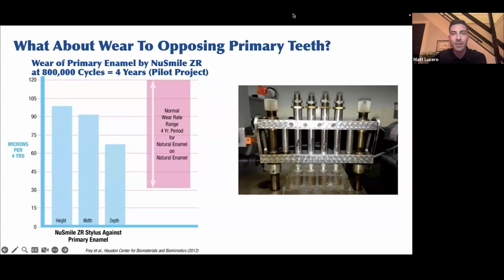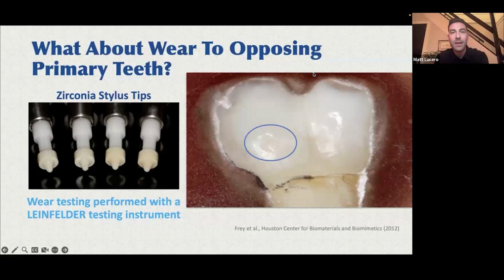So even with the zirconia restoration, a highly polished, glossy restoration, you're not going to get much wear to that opposing dentition. It falls into that normal wear pattern that we would expect to see. And these are photos from that same exact study. You can see the enamel. They put it into a resin, and then they would poke it a million times with that little stylus tip on that Leinfelder machine. And that's the wear that we saw. So nothing more than what we would typically see in a natural dentition, especially with some of our bruxing kiddos. They really beat up those teeth, even with their own natural dentition. And we just don't expect to see that with zirconia.